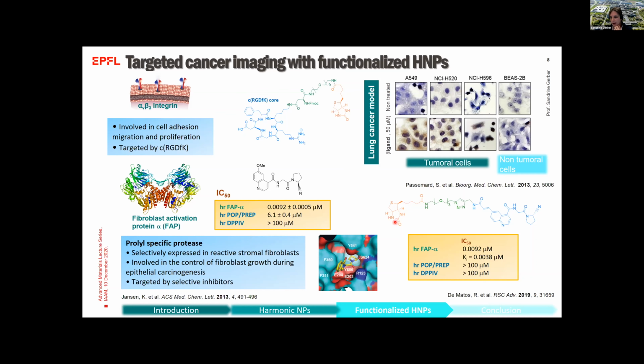So in our group, based on this work, we developed an analog of this substrate, linked here to a small spacer that will be used to make the conjugation at the surface of the nanoparticles. We observed that this ligand also has very specific recognition of the human recombinant enzyme and has almost no activity on the enzyme closely related to FAP alpha.